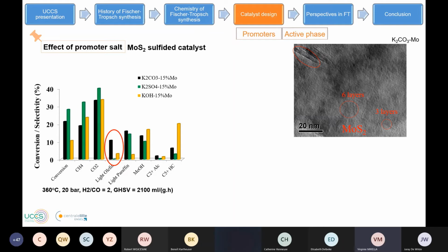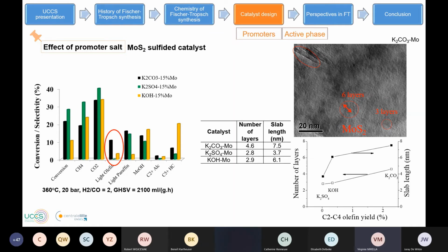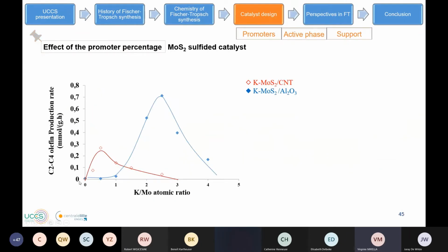So we have also observed the particle size on this catalyst promoted with potassium. For molybdenum sulfide it is a little bit different. We have studied the number of layers and the slab length of the layer to determine the particle size. And we have seen that when we have large particle size, we have better conversion, better selectivity in olefin. So larger particle size improves the light olefin selectivity. Then, as potassium brings basicity, we also studied the potassium to molybdenum ratio, and we observed that there's an optimum ratio of potassium to add to have a good selectivity in olefin.